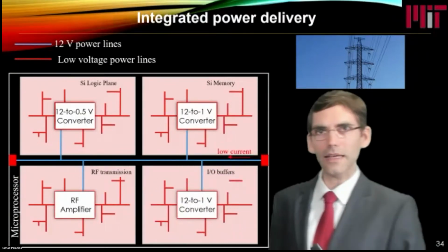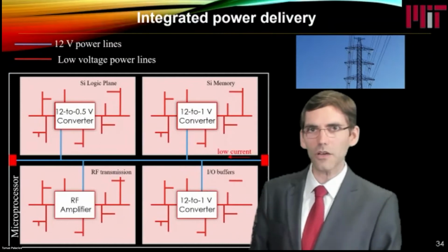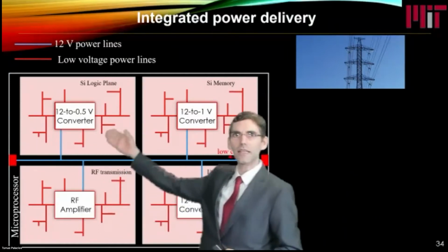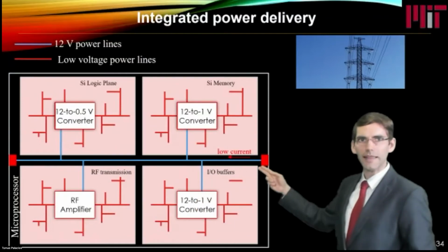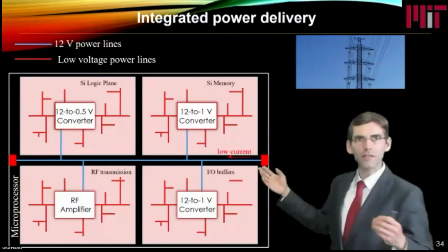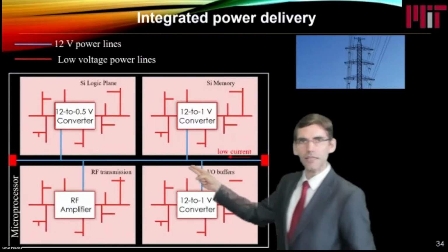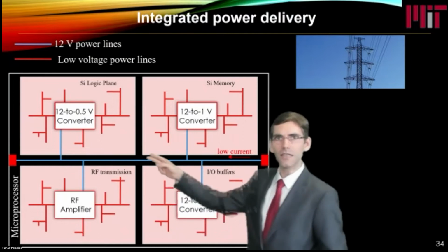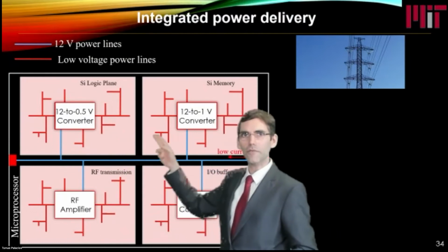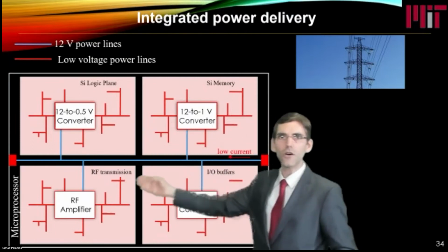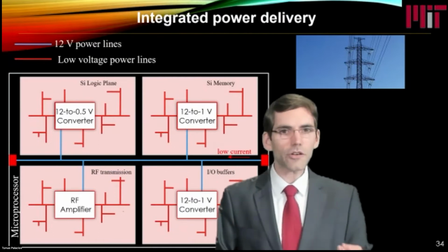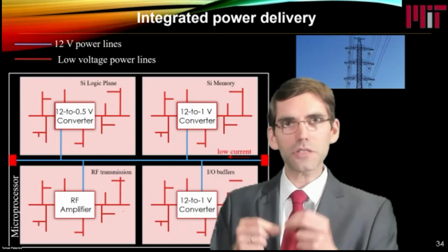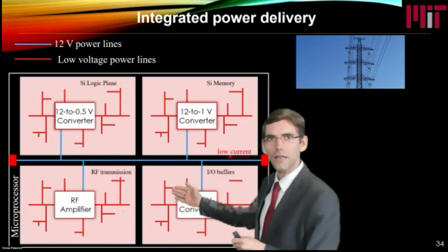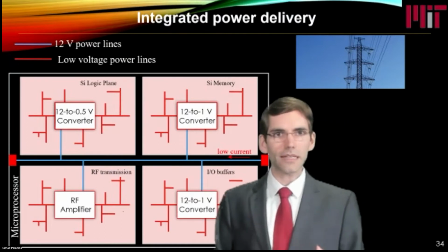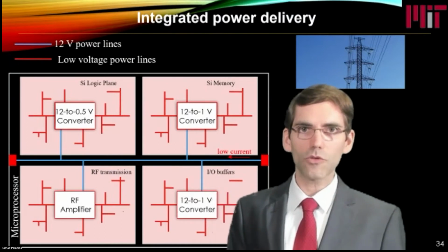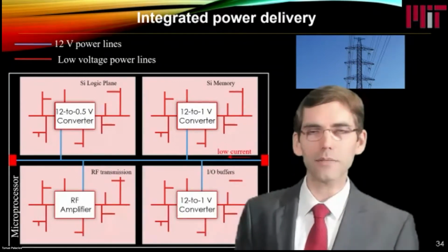And for that, the microsystem we are working on is a microprocessor, sketch here, where the energy is introduced at high voltages, around 12 volts, 12 to 20 volts, and low currents. It's distributed at these high voltages to minimize ohmic losses, and then locally is down converted to whatever voltages we need for the logic, the memory, or the RF communication. The question is, how can we make power conversion circuits that are small enough to be integrated with the microprocessor, but at the same time efficient enough to make sure we don't pay a penalty in terms of energy dissipation?